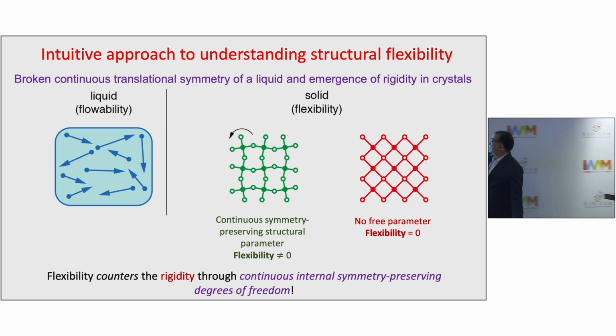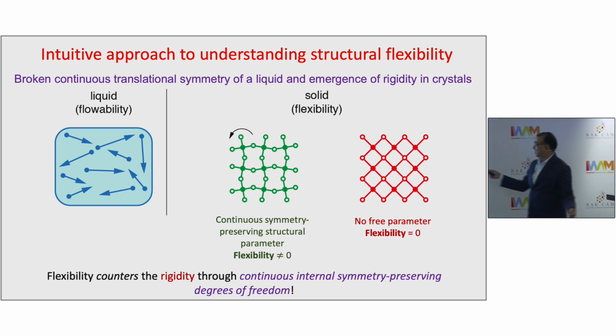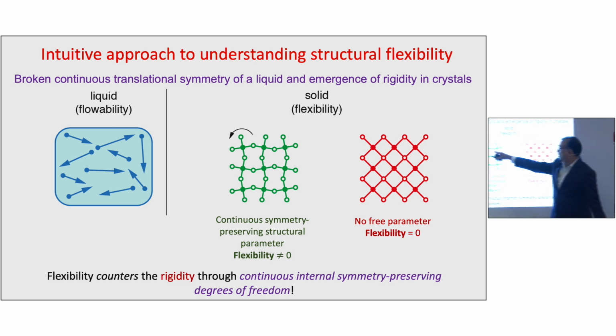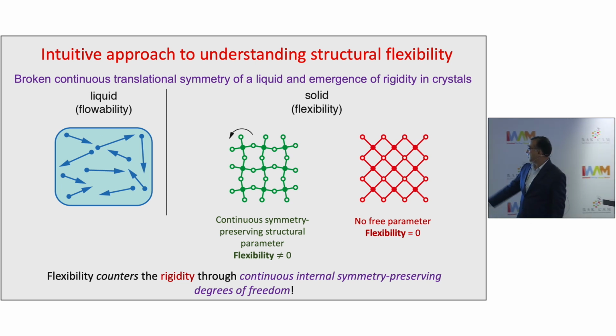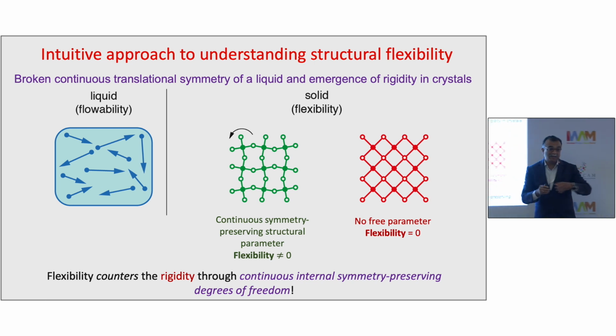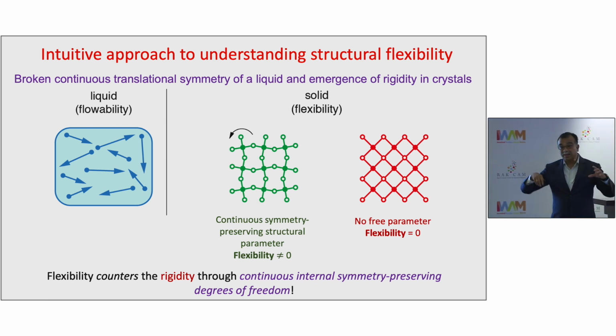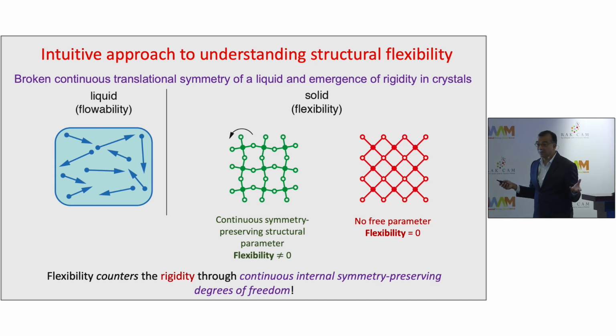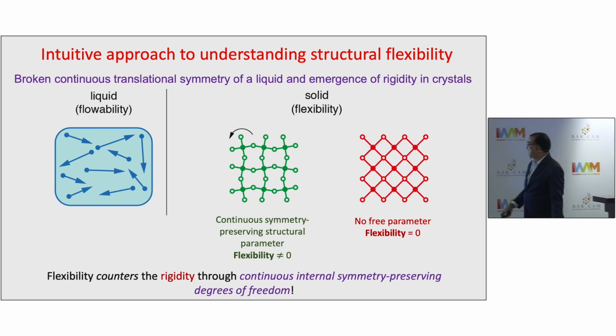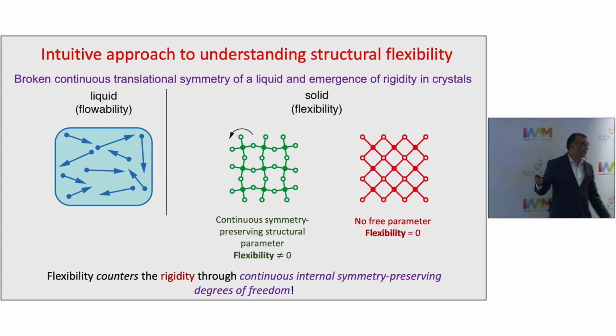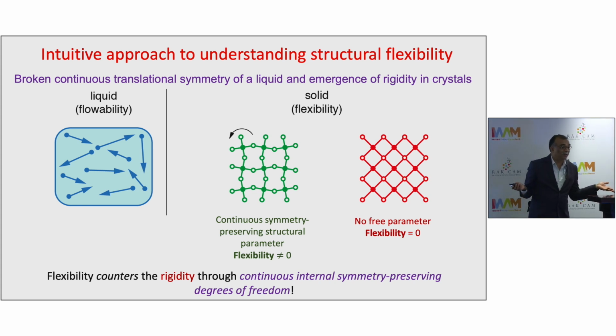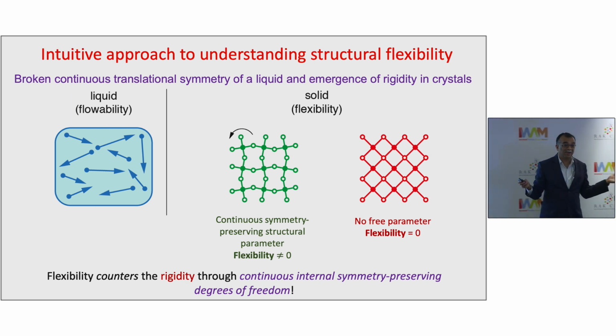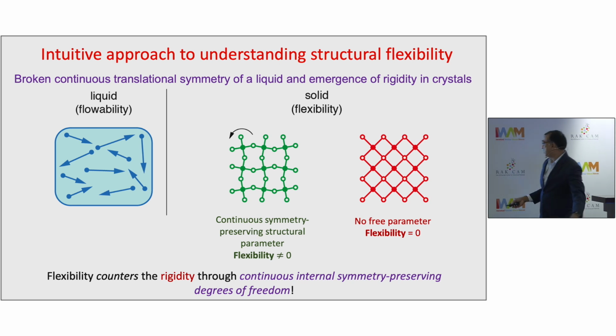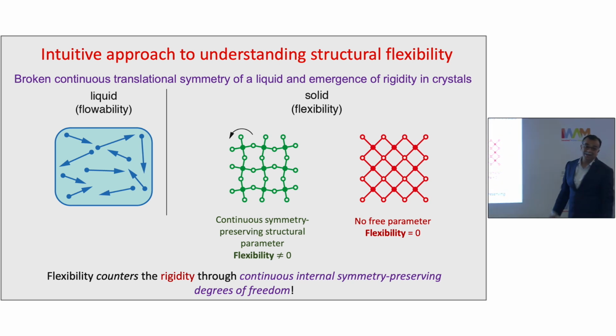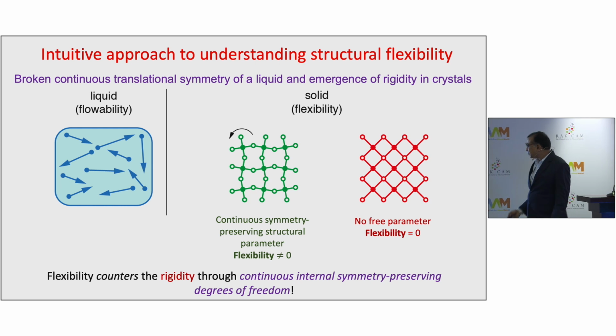So if I look at this solid and I apply stress to it, this has a lower symmetry and it can adjust itself. This angle, the buckling angle, can change in response to external deformation, and that's what is called internal structural rearrangement in response to external stress. Whereas this crystal, which has a very high symmetry, has no internal degree of freedom to adjust in response to an external field. If you compress it, the atoms stay on the same Wyckoff sites. So here flexibility is 0 in our notion of flexibility.